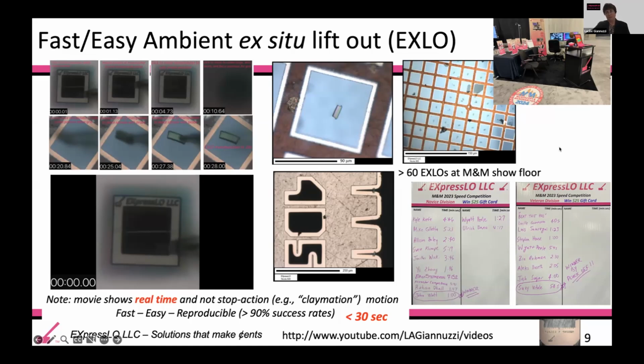And we have done lift out competitions at Microscopy and Microanalysis now for a number of years, where over the course of a show we have lifted out more than 60 specimens on the show floor. This would be extremely difficult to do with in situ lift out. Our competitions also consist of both novice division and veteran division, and even novices can be taught to do this technique in a matter of minutes. In this case, from 2023, we had a winner do it in just a minute, and we had a veteran do it in 54 seconds.